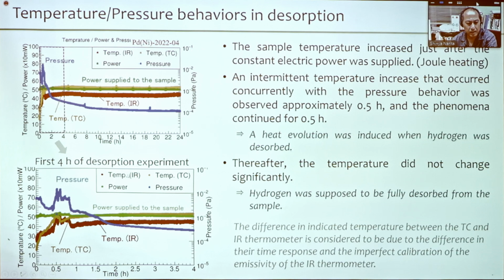Okay, so the bottom plot is the enlarged plot of the first 4 hours. Again, the temperature and pressure and the power supply to the sample. And now we found the sample temperature increased just after the constant electric power was supplied. So here and here, yes, so this is by the Joule heating. And after that, intermittent temperature increase occurred concurrently with the pressure behavior here and here. It happened approximately 0.5 hours after the beginning of the experiment, and the phenomena continued for about 0.5 hours.